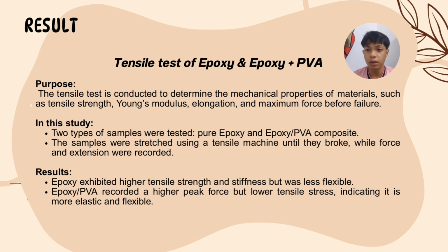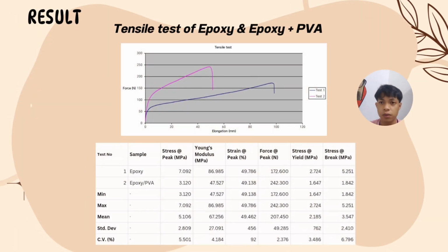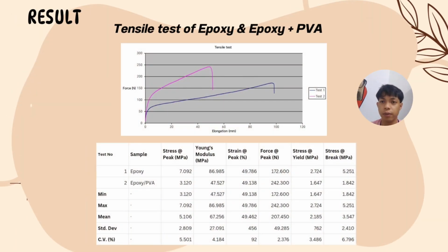The results show the epoxy has higher tensile strength and stiffness but is less flexible. Epoxy plus PVA, on the other hand, recorded higher peak force for lower stress, indicating it is more elastic and flexible. So this is the result from our test.